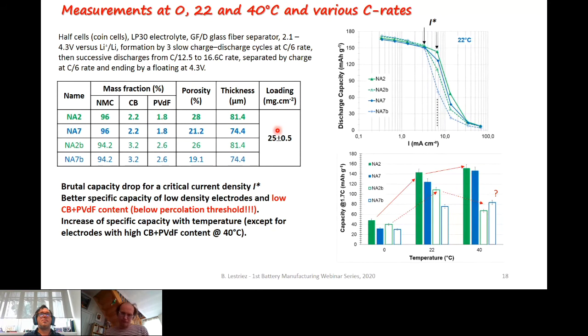So they are fairly thick electrodes, not ultra thick, but thick electrodes. When you look at the discharge capacity versus the current density, you see that at a certain specific current density, you have a brutal drop of capacity, which is a manifestation of ionic transport limitations. This is well identified in the literature.